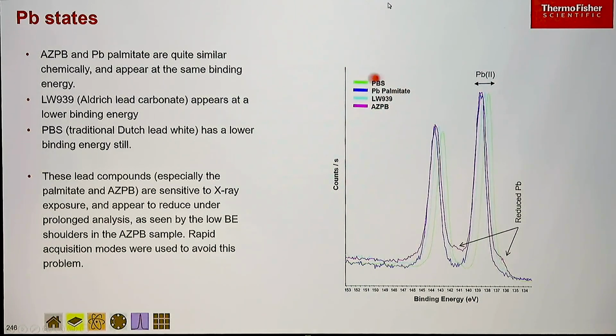So we collected a range of different lead compounds. So let me get this right. PbS is the traditional Dutch stack lead white. We've got just lead carbonate from Aldrich. Pb palmitate is one of these lead soap compounds, so it's an organometallic compound, and that has quite high binding energy. And then this AZPb is something similar to that as well. It's another organometallic. They're quite sensitive to X-ray exposure as well. So the longer we kept them under the X-rays, we actually started to see reduction to lead metal occurring. So you do have to be quite careful and quite quick when you're doing these experiments.